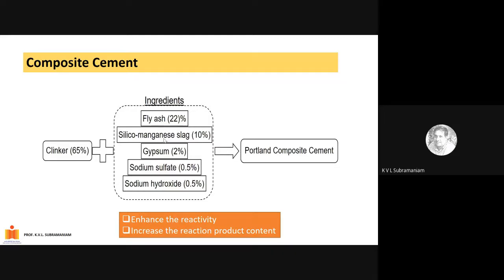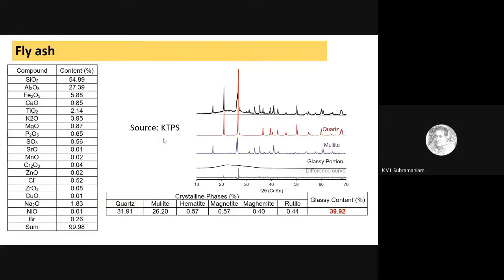So we brought these in, but we used a silicomanganese slag, which is basically a peculiar form of slag, which doesn't find ready use in the cement industry. So we basically used this material as our source. And of course, we had to add in gypsum, because in order to produce OPC with clinker, you have to bring in gypsum. And then we brought in some sodium hydroxide, and this was done in order to enhance the reactivity of fly ash. What sodium hydroxide does is it increases the alkalinity of the system, and that basically dissolves the glassy phase that is present in these materials. And the glassy phase is what contains the reactive silica. So it basically enhances the reactivity of the system. And with this, we produce the Portland composite cement, which contains clinker in addition to a mix of supplementary cementitious materials. Now, of course, we characterize the source materials.